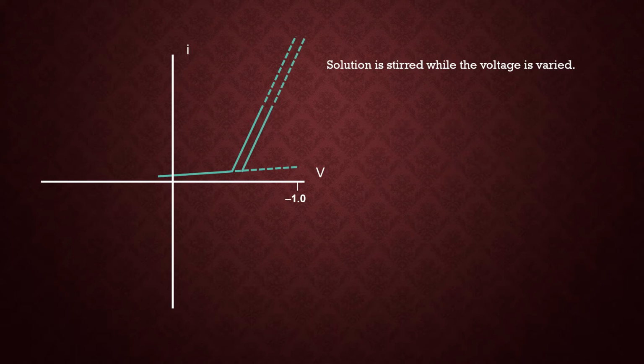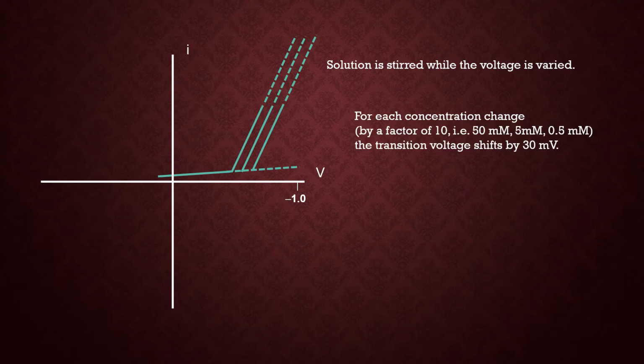If we now change the concentration, we would wind up seeing that the discontinuity moves. It changes with potential. And if we change the concentration by factors of 10, namely 50 millimolar, 5 millimolar, 0.5 millimolar, we would see that the transition voltage shifts by 30 millivolts with each factor of 10. If you remember from the Nernst equation, the factors of 10 in the log give you the 0.059 volts divided by n. Since 2 electrons are being transferred, you expect 30 millivolts shifts with each decade of 10 in the Nernst equation. Okay, so specifically this parameter. So as the nickel concentration changes by a factor of 10, you add to the potential 30 millivolts.